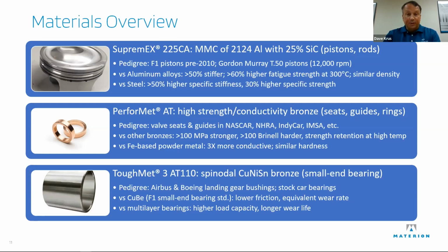And versus standard iron-based materials that are used in production automotive, it's 3 times more thermally conductive. It moves the heat 3 times faster, with the same hardness. And it's also not as stiff as the iron. So for a mating component like the head of the valve, it cushions it a little bit. It's much gentler on it.